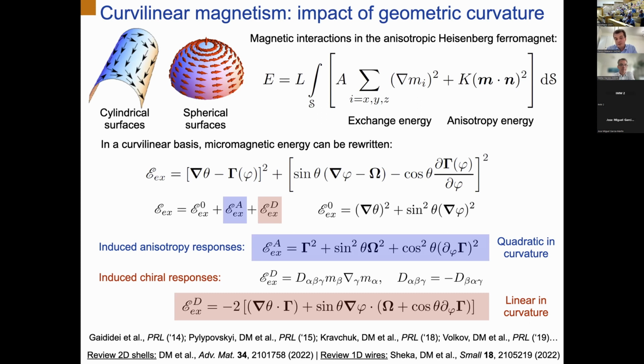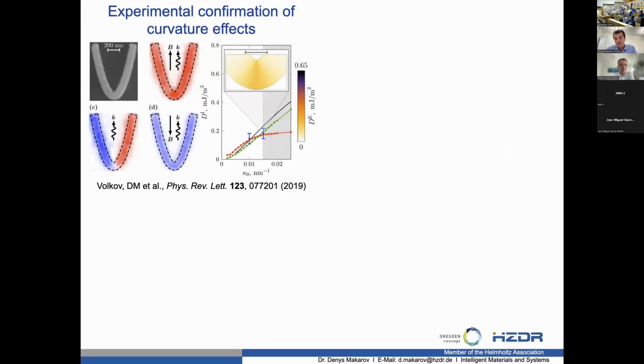These induced effects are not related to band structure modification. They are effects related purely to the geometry, the change of the geometry of a magnetic thin film, for example. What is important is that the curvature-induced chiral interaction, which in this case comes from exchange interaction, is linear in curvature, and it means that this effect is relatively strong, which allows you to even observe it. This is the work of Alexei Volkov. He will also give a talk a little bit later in the session.